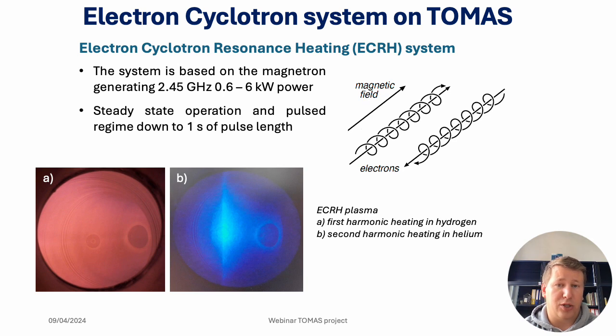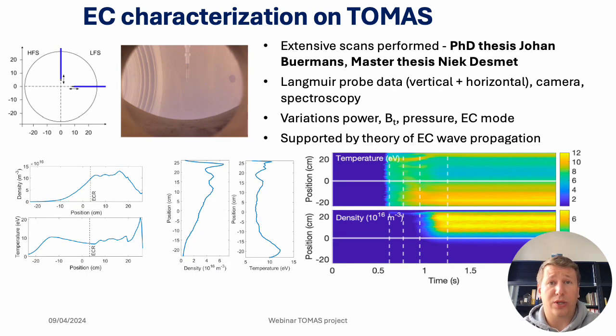in particular stray radiation. To achieve this, we use Langmuir probe, spectroscopy, and video diagnostics to collect information about plasma temperature and density distributions. Various scans are performed at different pressures, magnetic fields, electron-cyclotron input power, and wave polarization. For example, you can see the results of quasi-2D temperature and density scans done by our PhD and master students. We can define these parameters' spatial distribution and time evolution. These experimental results are used as a basis for the theoretical prediction of electron-cyclotron wave propagation, absorption, and conversion mechanisms.